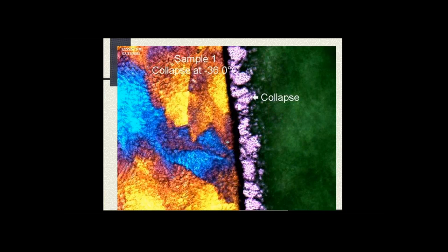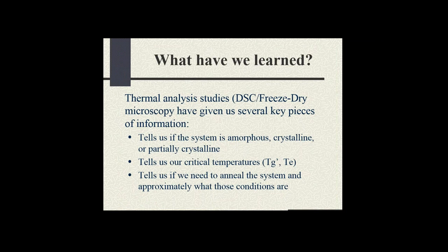Now, so I look at the DSC data, I look at the microscopy data, and we come up with what we call a critical temperature, where we can freeze-dry the product safely, or where we actually lose the product, and then we back that temperature down a little bit to make sure we're drying safely.